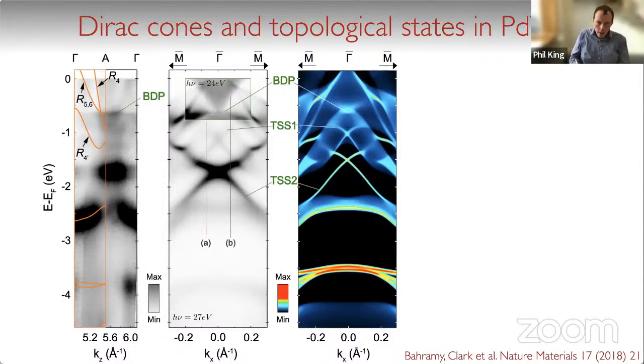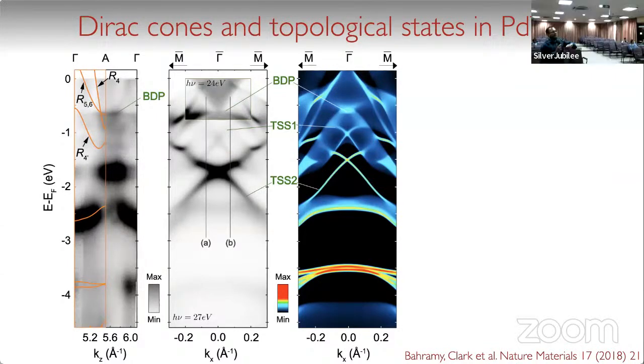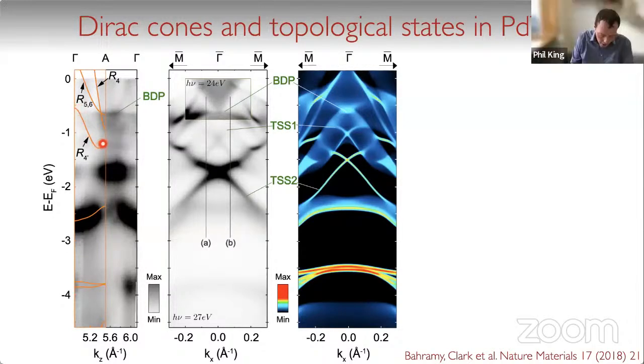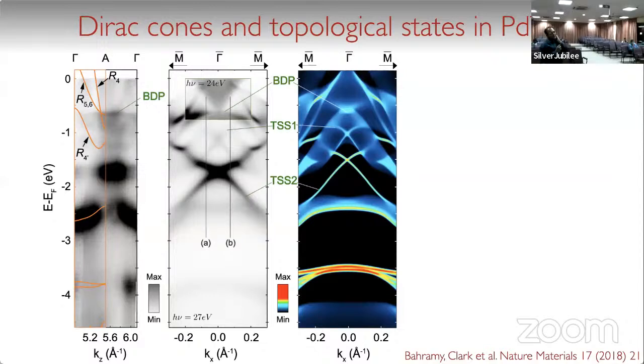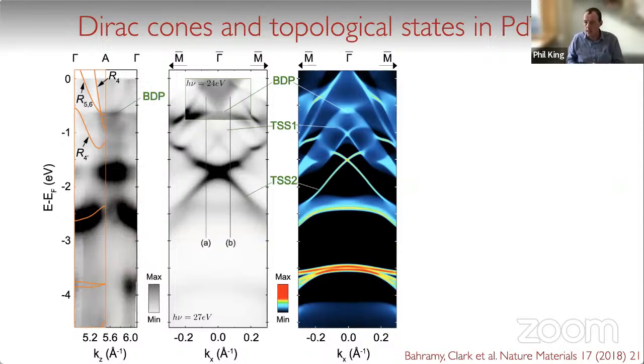Sorry, I think you're asking why I am describing TSS1 as a resonance and TSS2 as a surface state. Simply because surface state 1 here sits on top of a background of bulk states at some kz, and so it's really a surface resonance in the true sense of a surface resonance versus surface state. The wave function is peaked at the surface, but it extends deeper down into the bulk where it mixes with these bulk states. In contrast, TSS2 is a true surface state in a projected gap, and so the wave function is more localized at the surface.